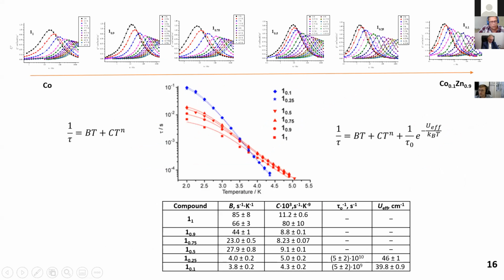So we did some measurements, at first to analyze magnetic properties. Here you can see all of them demonstrate slow magnetic relaxation in non-zero field. The relaxation process for cobalt-rich samples could be described taking into account direct and Raman processes, as you see in this curve. And for zinc-rich samples, we should take into account the Orbach process too. But the data are still not enough to analyze the structure of cobalt in the crystal lattice of zinc-rich samples.